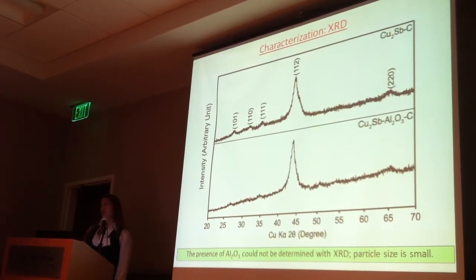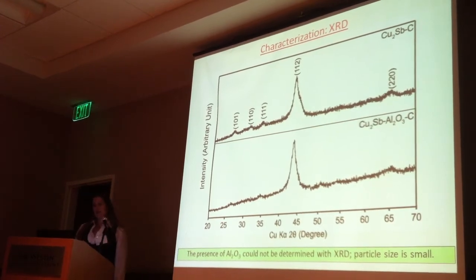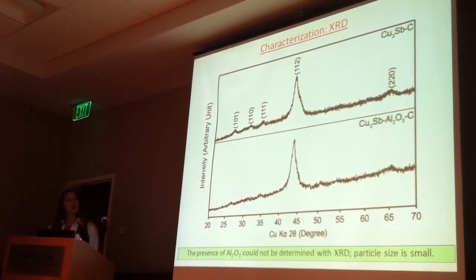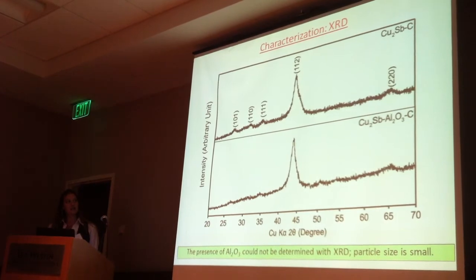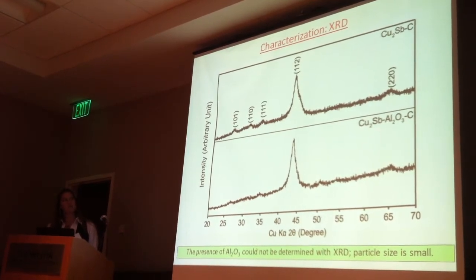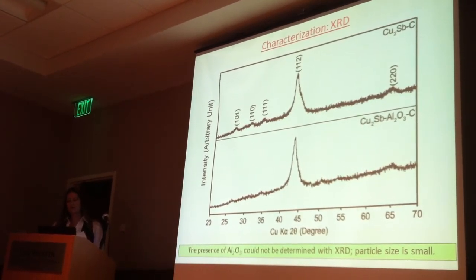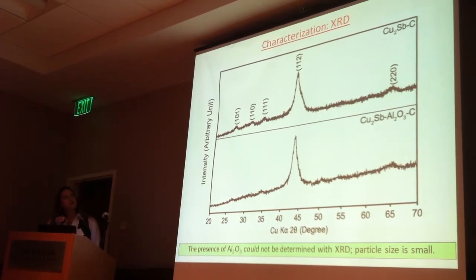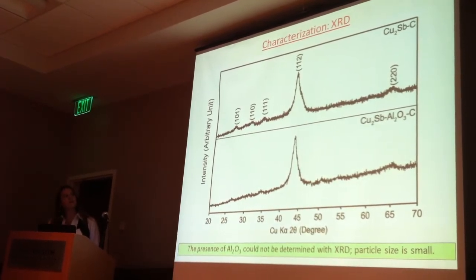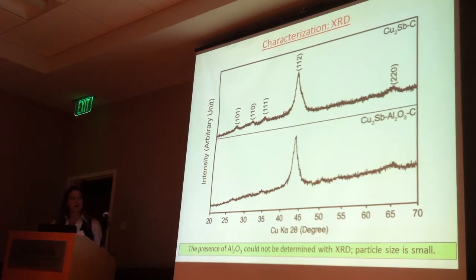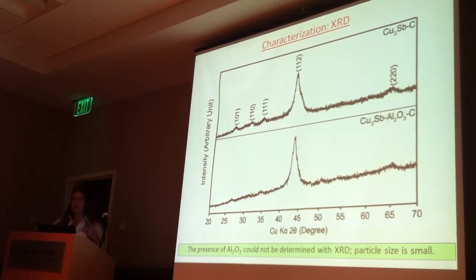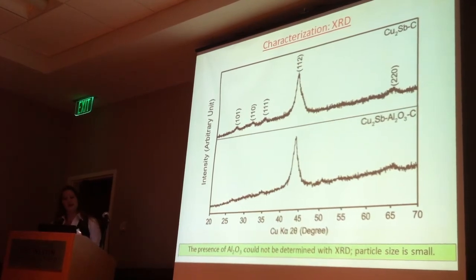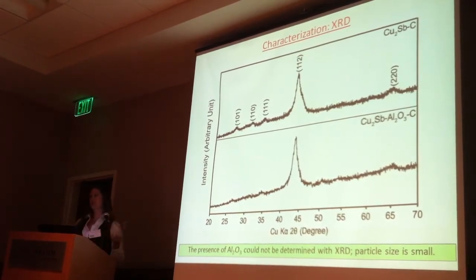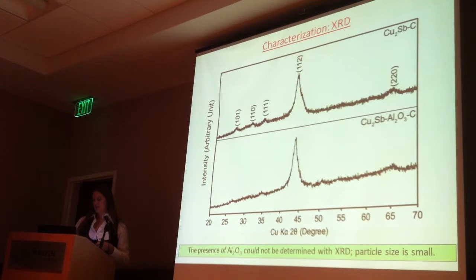So we wanted to figure out what exactly we had made in our ball mill mechanochemical reaction. And when we looked at XRD of this material, this is the one with the aluminum oxide, we weren't able to see basically anything. This peak corresponds to the same location for Cu2Sb, but it's very broad and not anything that we could really differentiate. Is this Cu2Sb or is this copper metal? And we also could not see any aluminum oxide from XRD.